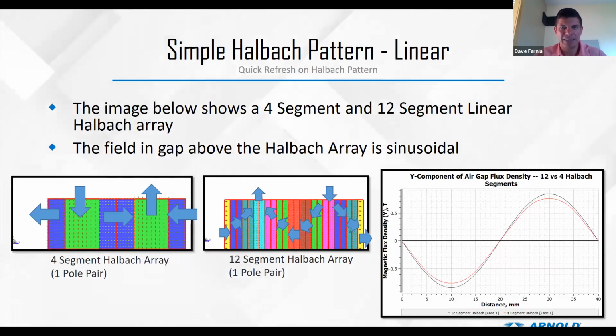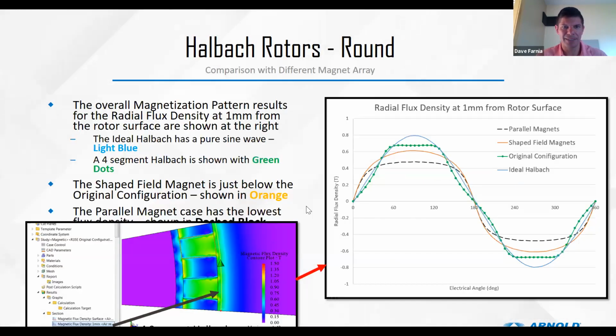Back on the rotor, we talked a little bit about the Halbach. They're very nice rotors. If we are doing a permanent magnet rotor assembly, we see the advantages of going to a Halbach array. The image below shows a 4-segment, let's say a simple Halbach array, versus a 12-segment Halbach array, and we find that the field above, the 12-segment, is more sinusoidal. It's shown in black, has a higher amplitude, so the 12-segment is going to get better performance in terms of that field in an ideal case.